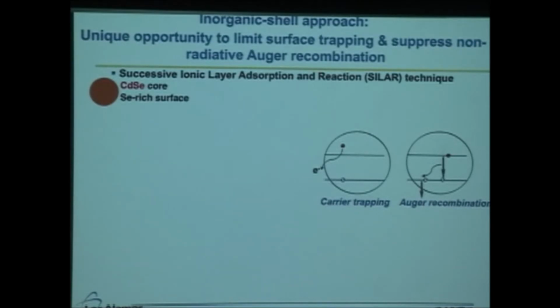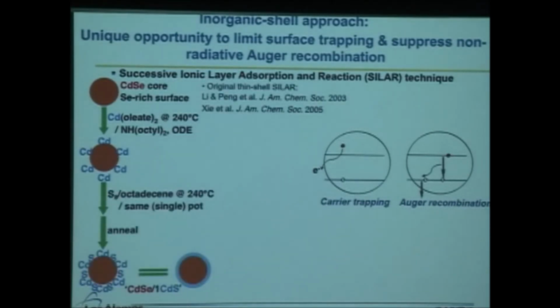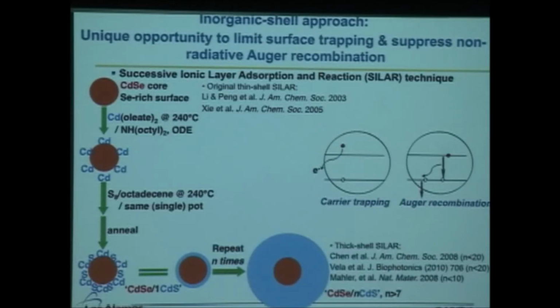At that time, we looked in the literature and found that the best approach to growing shells on quantum dots was the so-called successive ionic layer adsorption and reaction, or SILAR technique, which allows us to apply the shell material monolayer by monolayer, or actually half monolayer by half monolayer. We were able to do this many, many times. We significantly modified this procedure ultimately to create the control we needed to retain high crystalline quality even at very thick shells. We published this a couple of years ago now in JACS, and then we were followed by a group out of France a couple of months later, who had the same ideas apparently, and they have since published more detail.